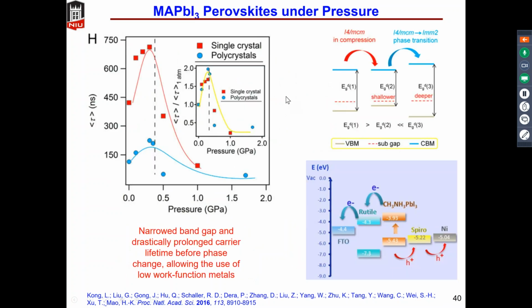And because of this shrinking of the lattice constant, some shallow defects become deeper defects, and originally deeper defects become shallow. And so we also noticed that the carrier lifetime before the phase transition increased. But after the phase transition, the carrier lifetime continues to decrease. So this carrier lifetime change also follows the phase transition.